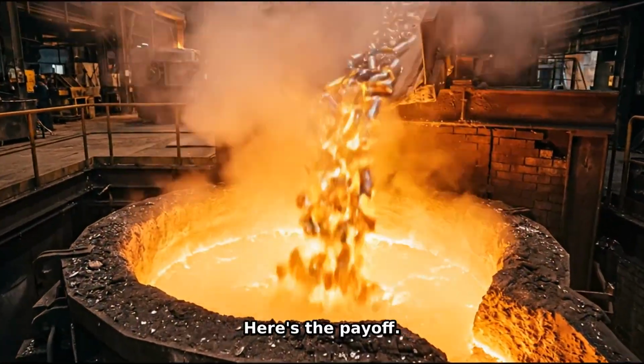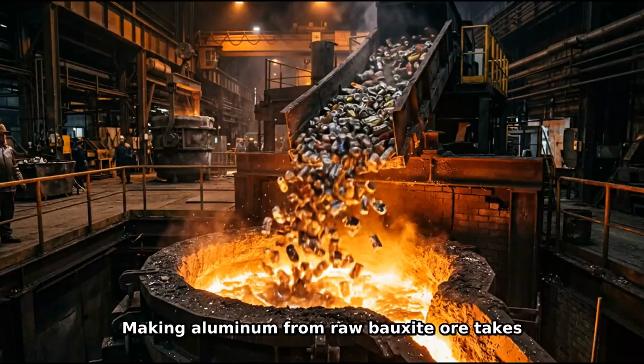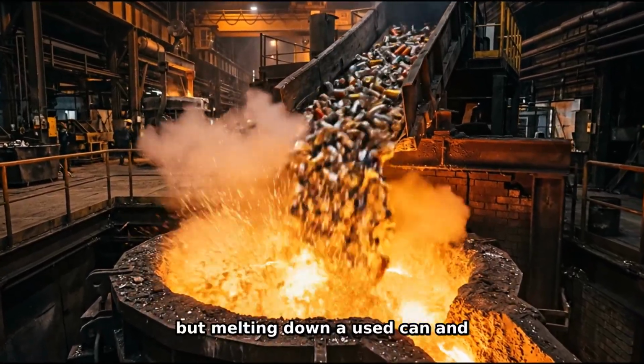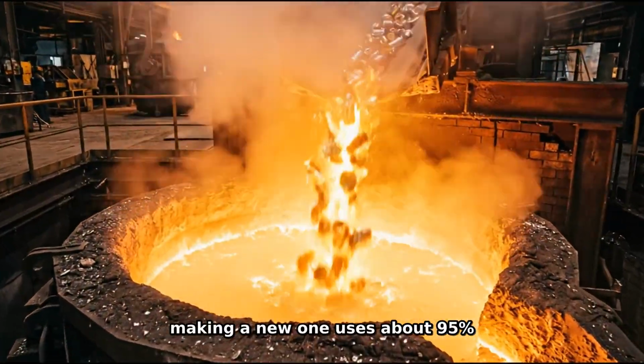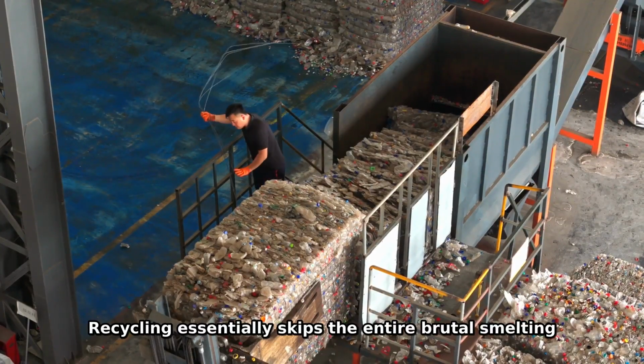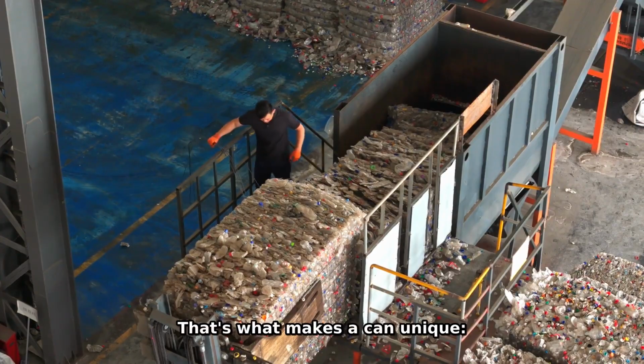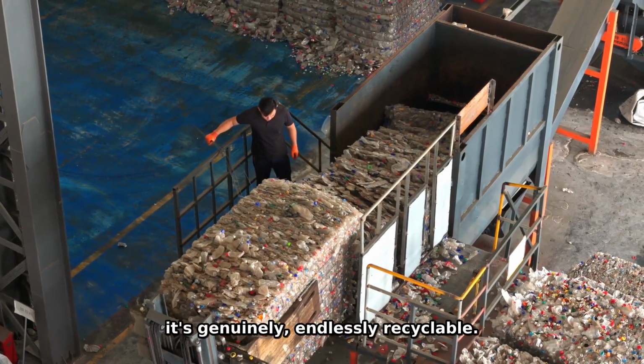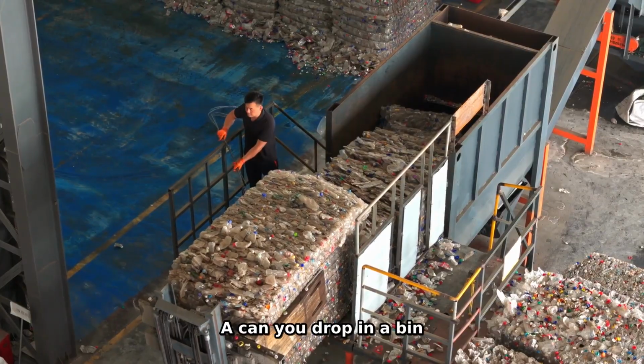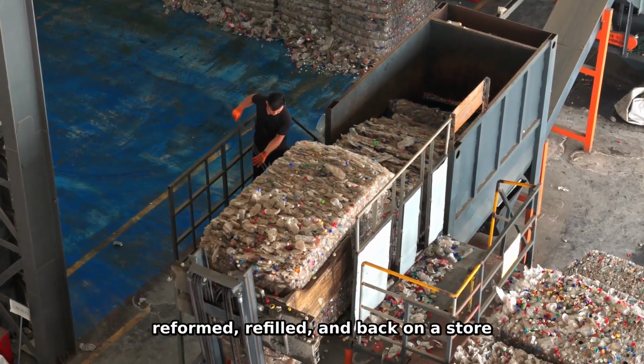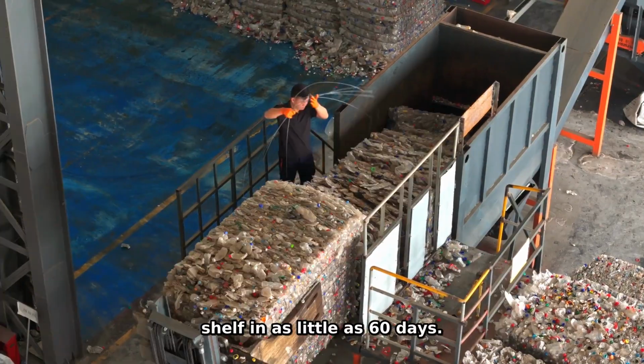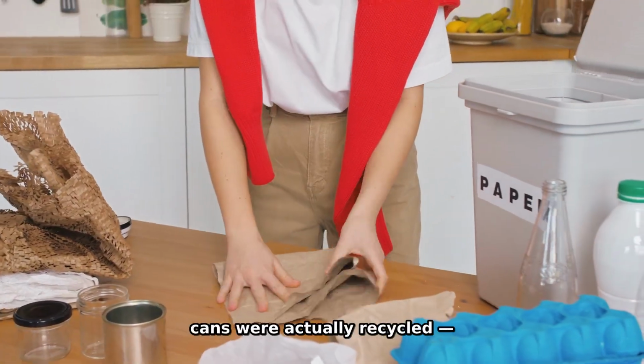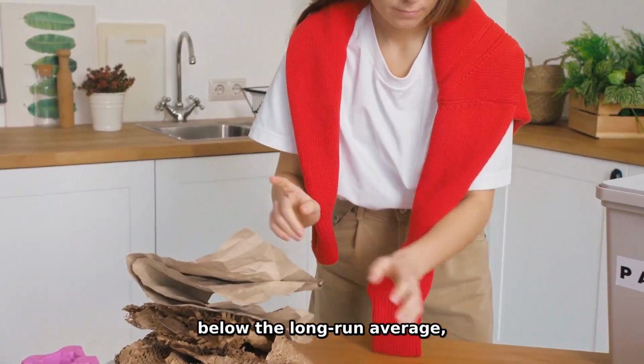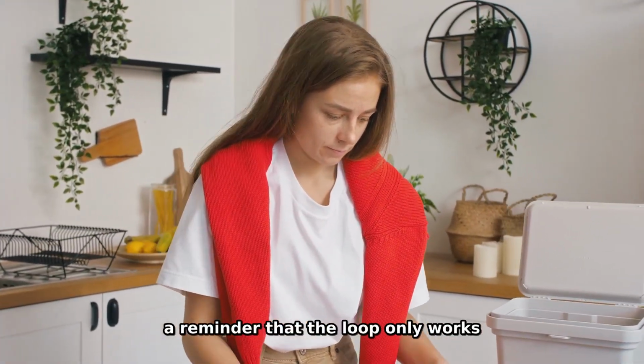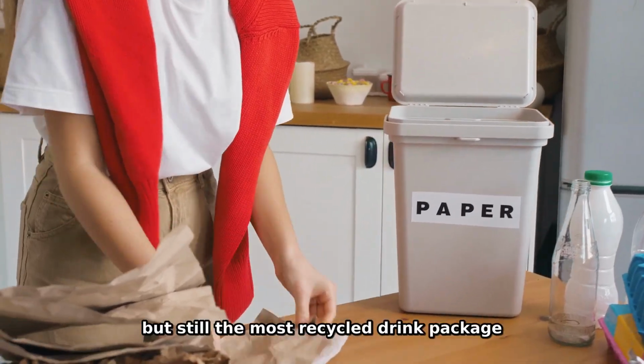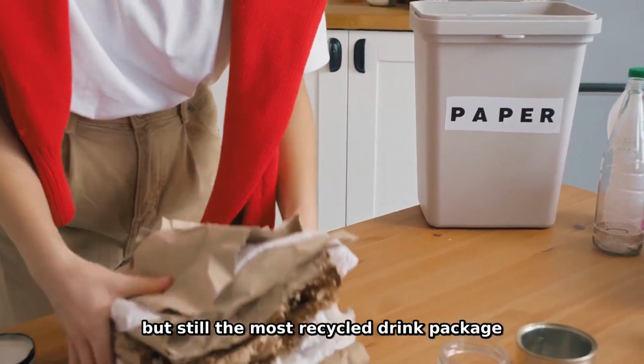Here's the payoff. Making aluminum from raw bauxite ore takes enormous energy, but melting down a used can and making a new one uses about 95% less. Recycling essentially skips the entire brutal smelting step. That's what makes a can unique. It's genuinely, endlessly recyclable. A can you drop in a bin can be melted, reformed, refilled, and back on a store shelf in as little as 60 days. In 2023, about 43% of US cans were actually recycled, below the long-run average. A reminder that the loop only works if we close it, but still the most recycled drink package there is.